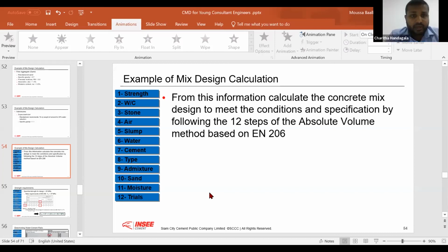Okay, and another one, sir. How to add fly ash content to the mix design? It's by Mr. Tarindu. Okay, there are two different ways, even three, depending on the quality of the fly ash. We have standards. When the residue on the 45 micron is below 35%, you can take this fly ash and blend it with a finished product like cement.